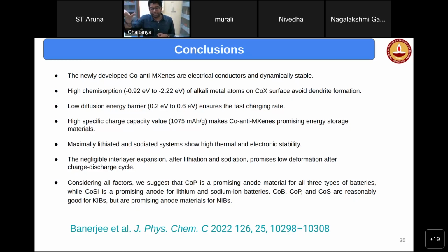And in order to understand the adsorption, why there is a stronger adsorption, etc., there is also population analysis, which I did not show you here, but we perform. What I have shown you is the charge density differences, which we used to explain the higher stability at a particular site compared to the other sites. If you remember, the S3 site was the most stable site, and at the S3 site, the charge density between the lithium atom or any metal atom and the non-metal atoms is higher.